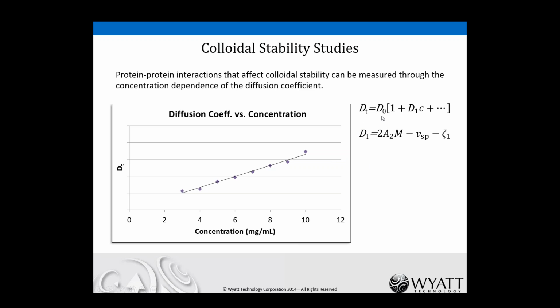Mathematically, the translational diffusion coefficient can be represented as a simple series expansion. So we have D sub 0, that's the diffusion coefficient of an individual particle, and then the first coefficient of concentration, D1, which is known in the literature also as k sub D, is the first order behavior representing the self-association or self-repulsion. It is related to the second virial coefficient, A2, otherwise known as B22, including some other terms that are due to hydrodynamic behavior.